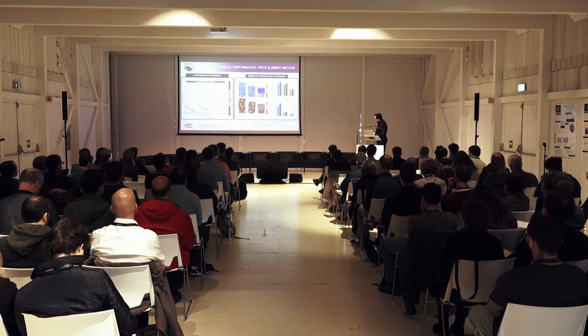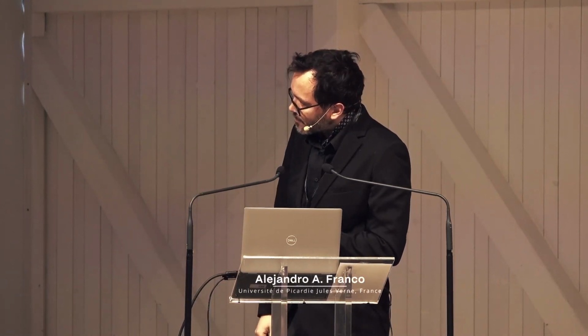And this simulator can also provide insights on where the lithium is going to be intercalated in the active material in 3D. This is more like simulating operando experiments, right? In operando experiments for lithiation, the lithiation dynamics, okay? That will also be very useful for industry because they can really see in 3D where the lithium will go as a function of the quality of the interfaces between active material, carbon binder, and pores, right? And then you can get other descriptors that I'm not going to comment on now because of time.